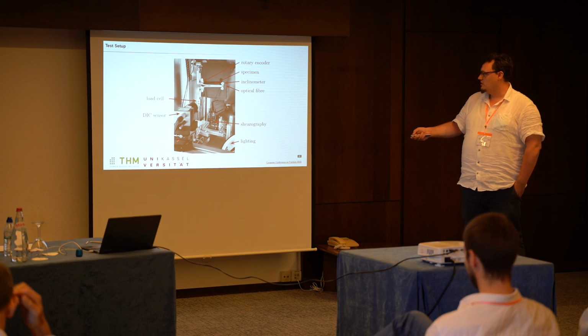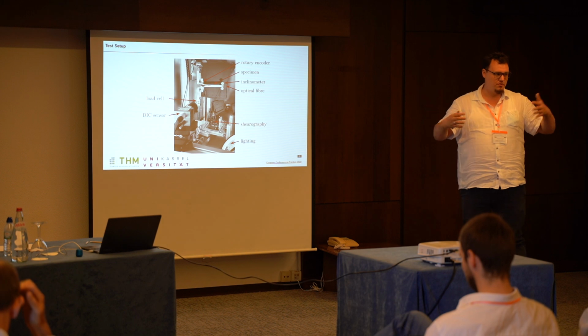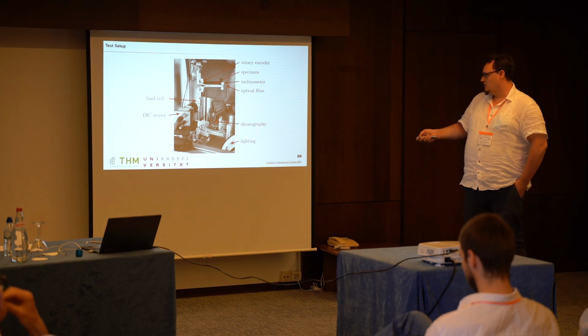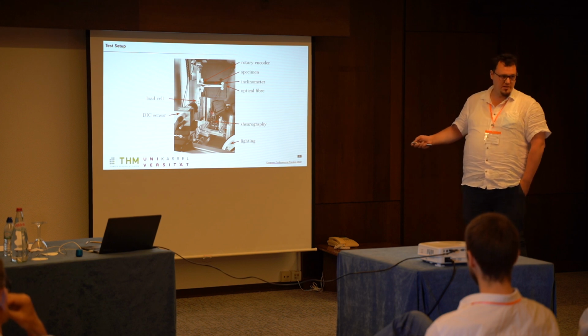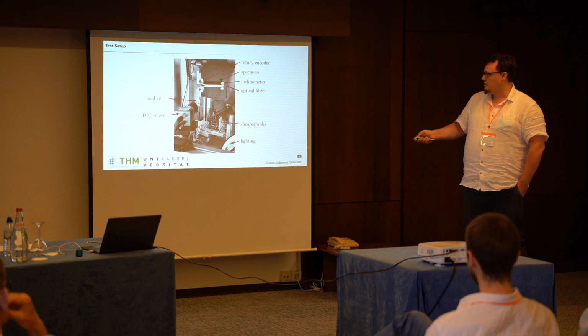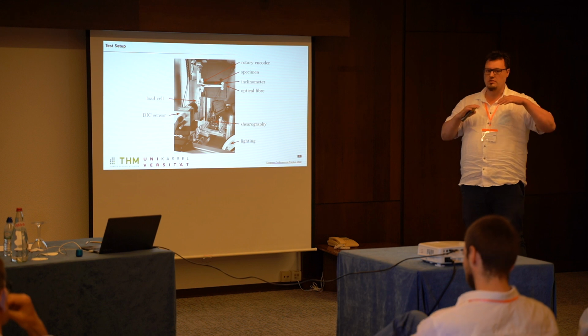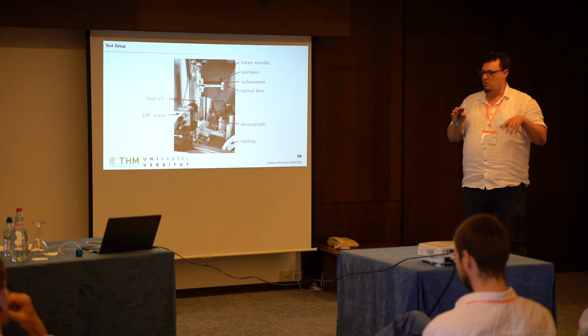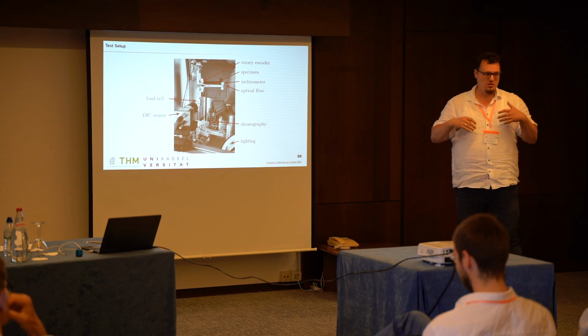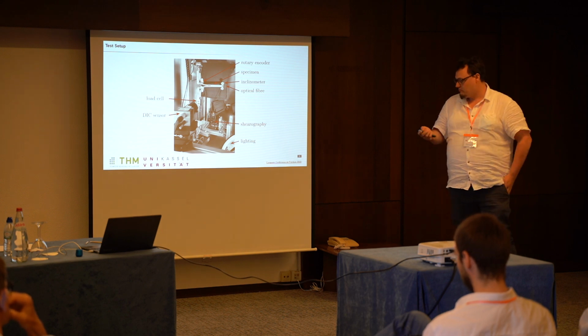In front of the picture, there's the DIC sensor. We have 2 of these for 3D measurement. Additional lighting, and below there is the shearography system. With this we measure the deformation on the lower surface of the adherend. We perform all 3 measurements simultaneously.